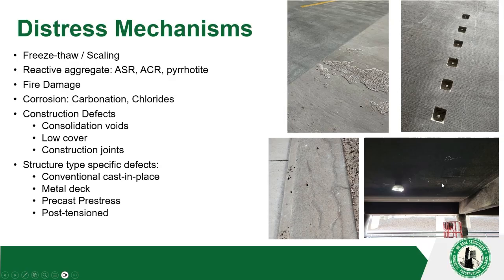Now, fire damage is something that happens in a lot of garages. You may not hear about it too often, but cars do catch on fire. Electric cars do catch on fire. And this one right here was completely covered with fire. We ended up checking this beam right here, and we found out that it was actually okay, but the concrete cover had cracked completely. Then we have construction defects, and then we get into the different specific types of defects that are related to different structures, and especially the post-tensioning and pre-stressed concrete are quite unique.